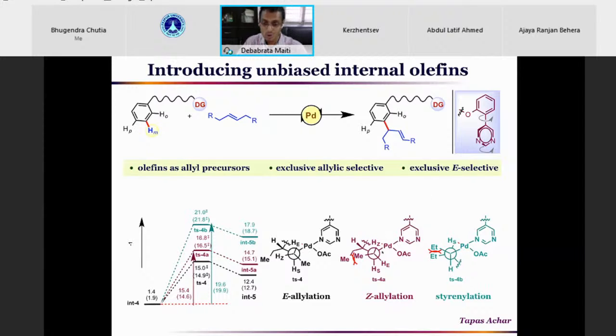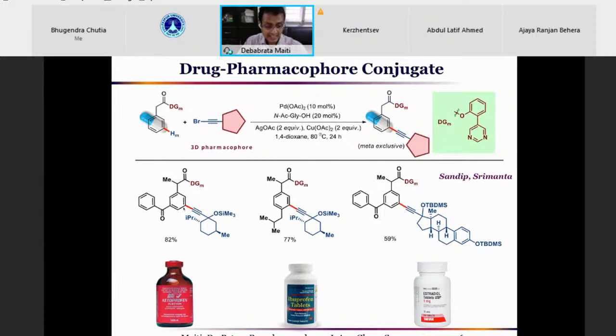Very recently, we were able to show that even one of the most difficult reactions, such as incorporating unactivated internal olefin, can be done as well, and we are getting exclusively the E product. That's again with the same biphenyl pyrimidine based ligand, which is doing the chemistry. We can do the inverse Sonogashira type of reaction. Once again, a very exciting reaction with the help of CH activation. So the meta-CH bond is selectively activated, and with an alkynyl halide, we can do the meta-alkynylation reaction. A number of drug molecules, pharmaceuticals, agrochemicals, and pesticides can all be decorated with the meta-alkynyl group.